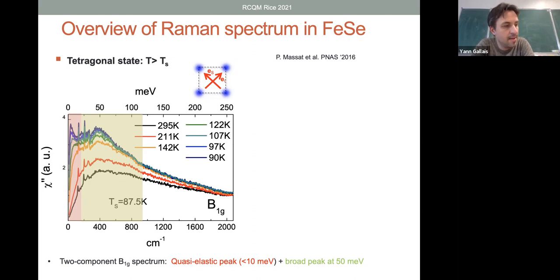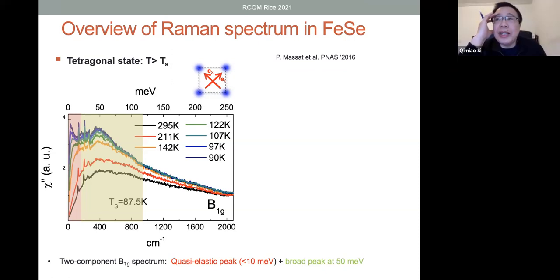That's the first comment. For iron selenide with sulfur, I think the fingerprint of quantum criticality is not that obvious, because the transport measurements see linear-in-T behavior, but that actually is in the ordered phase. So the best data that show linear-in-T behavior are in the ordered phase, which is not what you would expect in the typical QCP scenario. And there is little evidence also of any effective mass enhancement. So in this sulfur iron selenide phase diagram, I think the evidence of quantum criticality is not that solid up to now. And I tend to agree. We had talks by Nigel Hussey and Amalia Coldea earlier in the series, and maybe they have slightly different wordings, but I think the data were consistent.